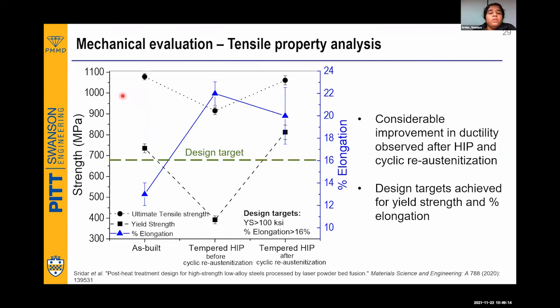If you see the actual values, what we see is that the yield strength has improved a bit, just a bit, I would say, but it has improved, and it is well above the design target even in the as-built. The design target is 100 KSI, which I told is pretty close to 700 MPa, and the elongation is 16%. If you see the yield strength curve, the one with square symbols, the yield strength in the as-built is slightly lower than the one for tempered HIP after cyclic reaustenization.